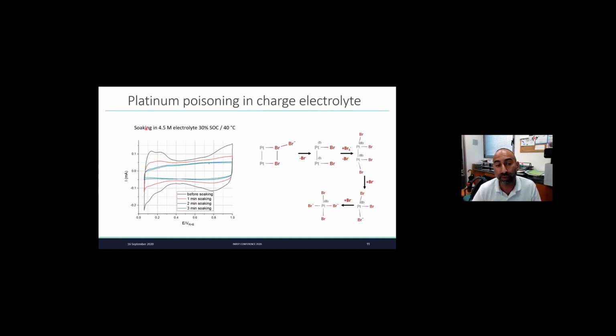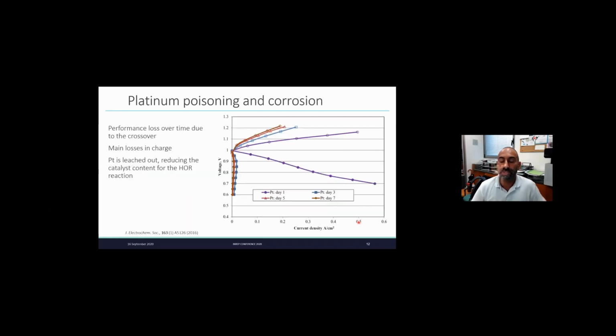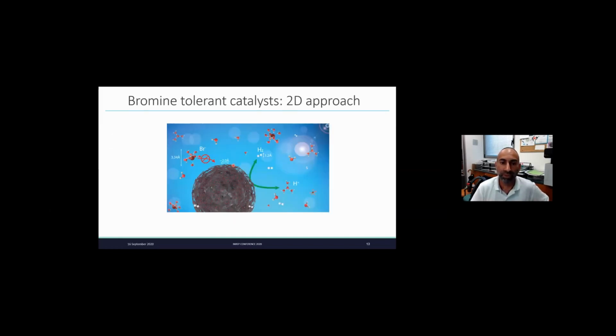And if you go to soaking into a charged electrolyte, it's even worse than that. In a few minutes, 3 minutes, you just completely strip your platinum out, and it gives some bromidric platinic acid. So it was done also in cells, and in cells you have here the initial charge, discharge in day 1, and after a few days you can't discharge anymore your cell. So it's really an acute problem.